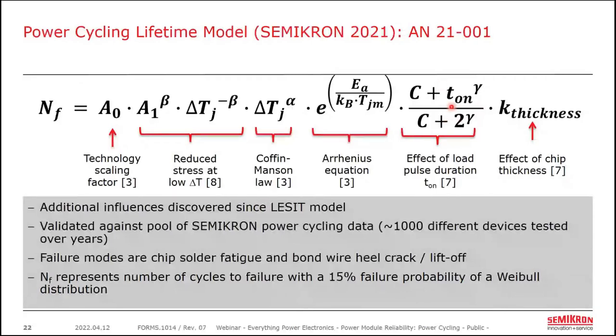And so Semikron has derived this particular model from a very large pool of power cycling tests that we've done over the years on a variety of different module types. And the differences in construction between those module types are factored into this technology scaling factor. And as we discussed before, we still define a failure as a 20% increase in on-state voltage drop. And so in the range of heating times, T on, that this model has been validated for, the actual failure mode ends up being either chip solder degradation or bond wire crack liftoff.